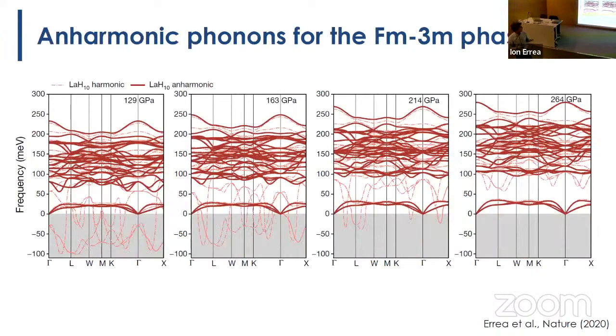Also on the phonons, obviously. If we look at the phonons of the high symmetry phase below, let's say, 230 GPa, we have instabilities. The second derivative of the Born-Oppenheimer energy surface is concave for many distortions. This is what phonon instabilities, negative phonons, mean: for many types of q, many possible distortions lower the Born-Oppenheimer energy, so this structure is not a minimum of the Born-Oppenheimer energy surface. But on the other hand, when we calculate the phonons from the free energy Hessian, the second derivatives of the free energy, including these quantum anharmonic effects, this high symmetry structure is stable. So it is a minimum of the free energy landscape that includes these quantum anharmonic effects.